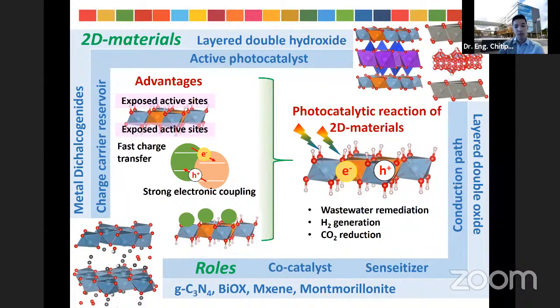The contact between these 2 materials can prevent the recombination of the electron-hole pair, leading to enhanced photocatalytic activity. The photocatalytic reaction of 2-dimensional materials is similar to that of a normal photocatalyst. Under light irradiation, it can generate electron-hole pairs on the surface of the photocatalyst, and the electron and hole can further react with water or oxygen to produce active species for the decomposition of organics present in wastewater.